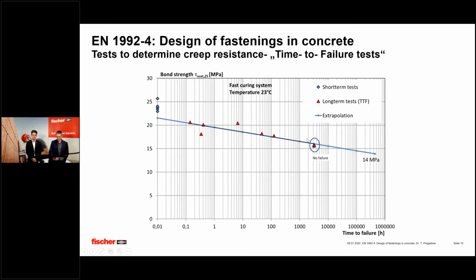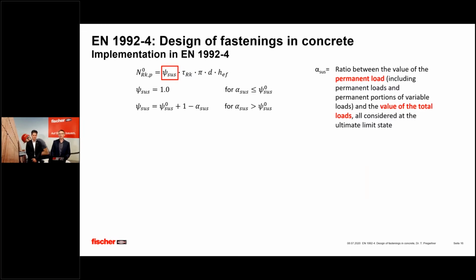Now, if you extrapolate these values of the time to failure test to the service life of 50 years, then you end up at roughly a drop of the transferable bond strength at the end of the service life of your fastening of roughly 40% to a value of 0.6. And this value of 0.6 found its way into the design equations for this combined pull-out failure mode. On the top left, you see the equations for the single anchor without edge influence and without spacing influence. It is calculated with a characteristic bond strength and a surface area.